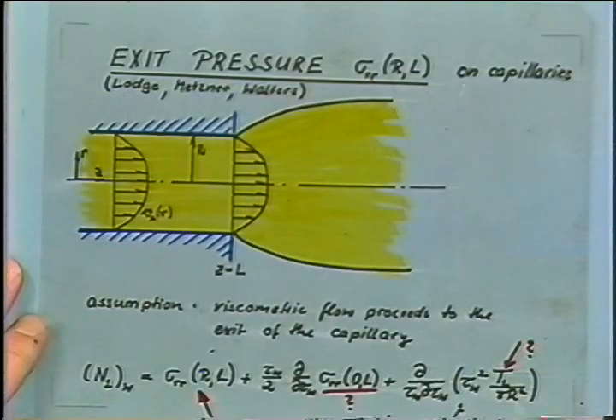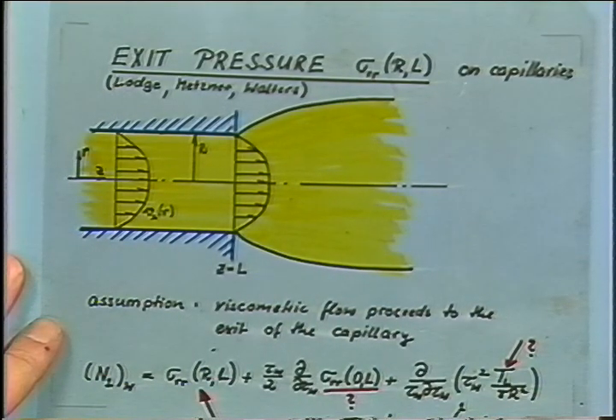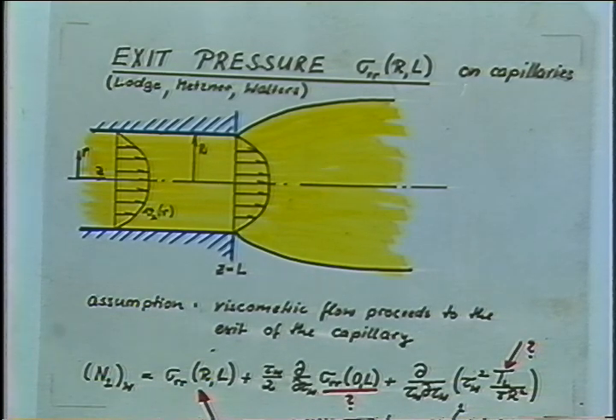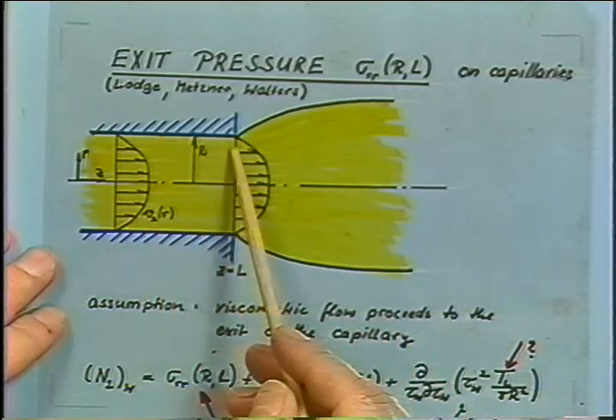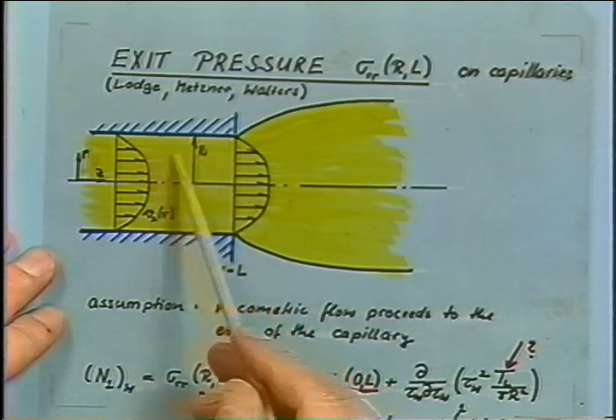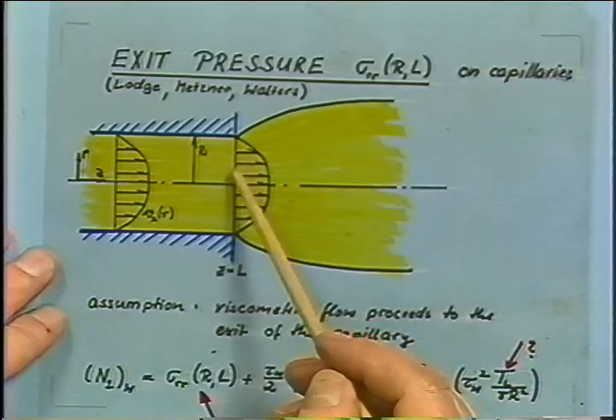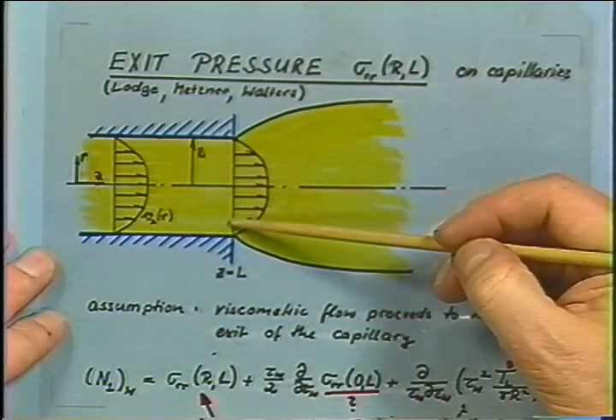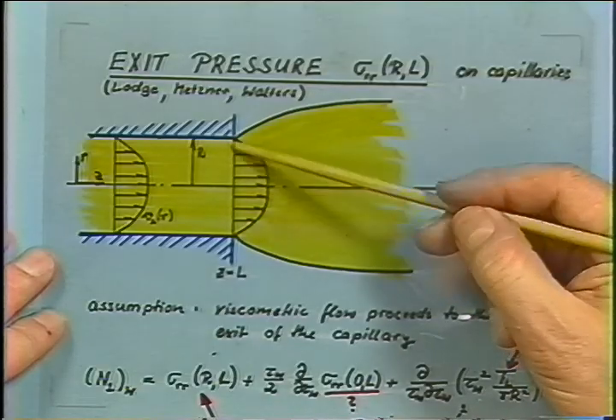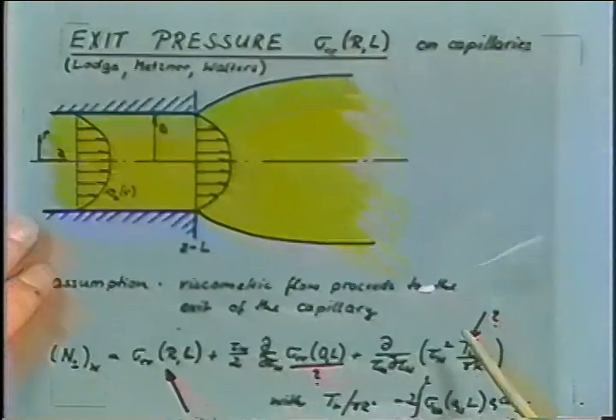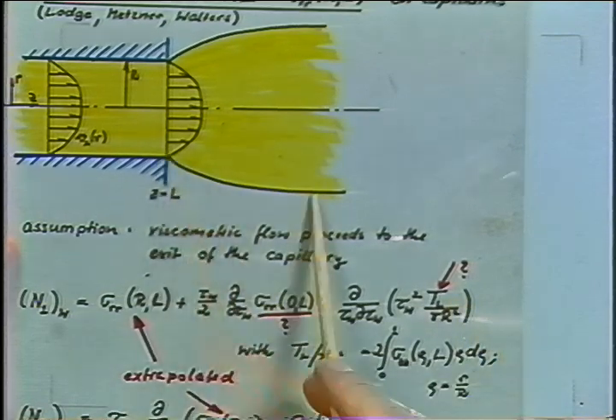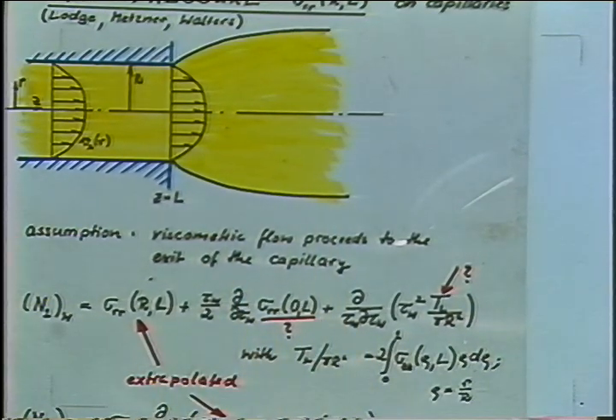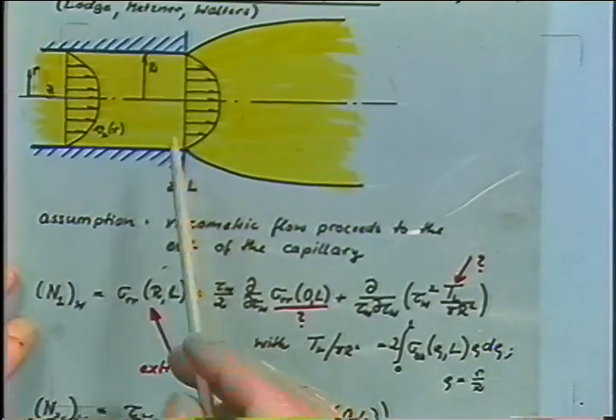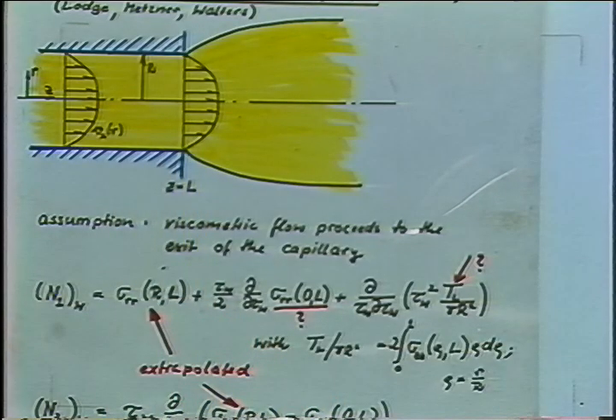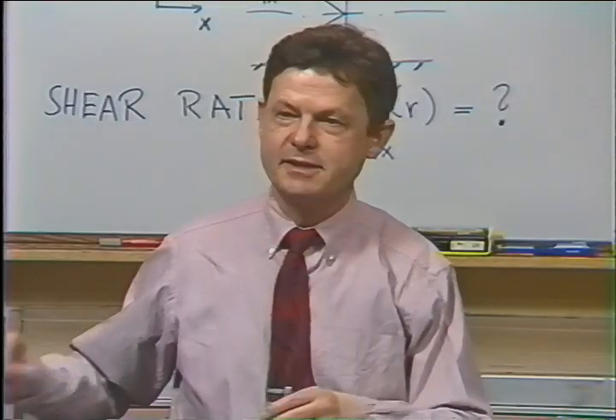The other possibilities where the tension can be measured: normal stresses in the polymeric liquid appear not in a flow with straight streamlines, but as soon as we change the flow, if we go from this type of flow to some other flow, we would maybe be able to guess the normal stresses on the streamlines, and the integral of the normal stress over this area gives rise to total tension on the extrudate. We could measure the tension on this extrudate and then analyze the flow with a lot of assumptions. Basically, we would have to assume something about the stress at the center line, and then we would come up with some information on the normal stresses. But it's a very biased analysis, I would say.